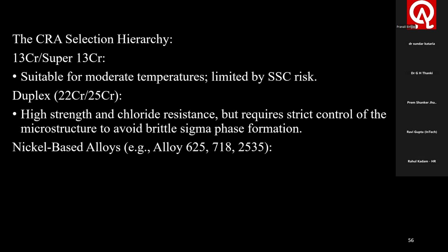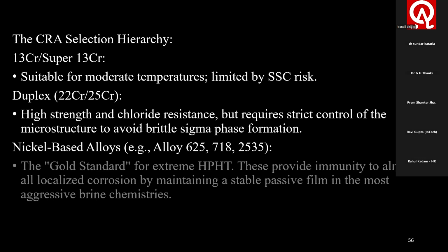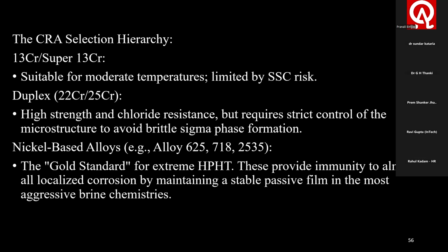Nickel based alloys, alloy 625, 718, 825. The gold standard for extreme HPHT. These provide immunity to almost all localized corrosion by maintaining a stable passive film in the most aggressive brine chemistries.